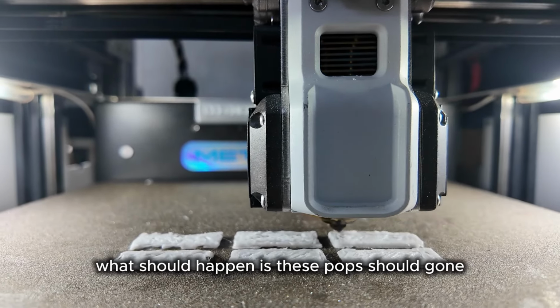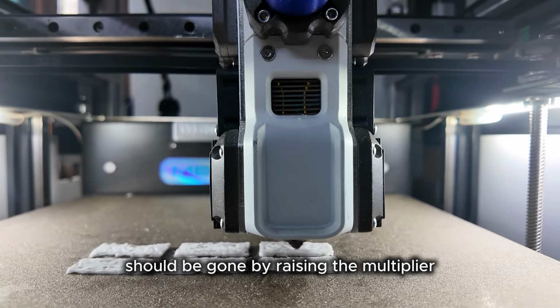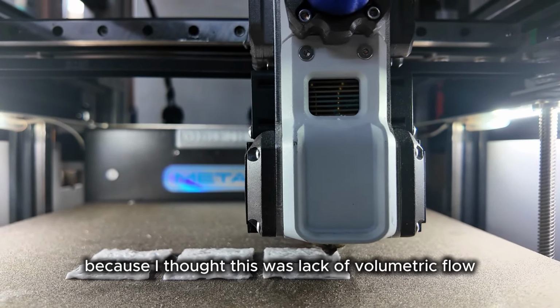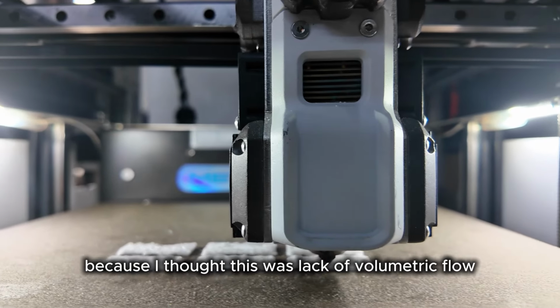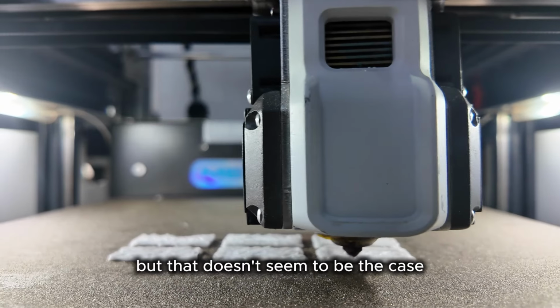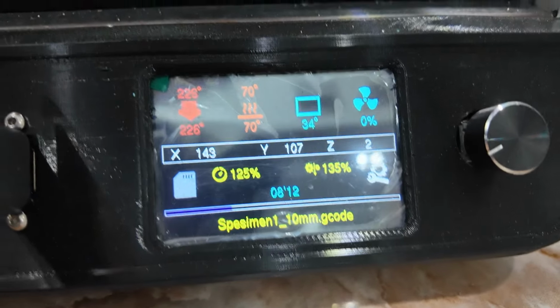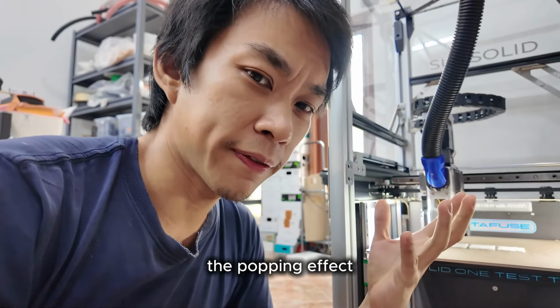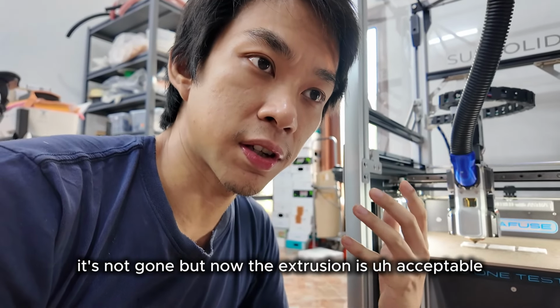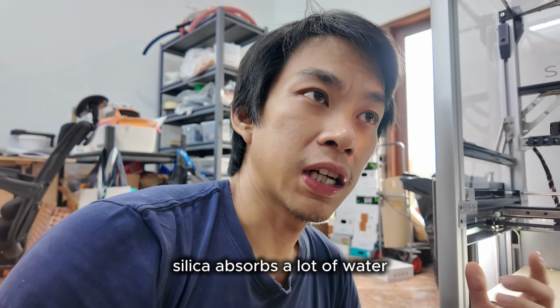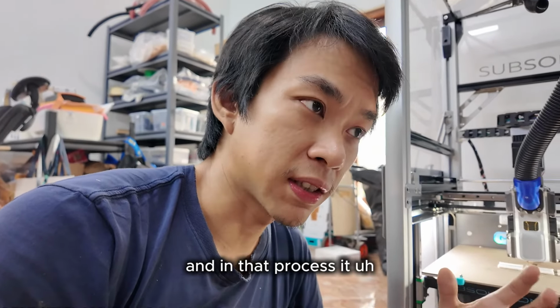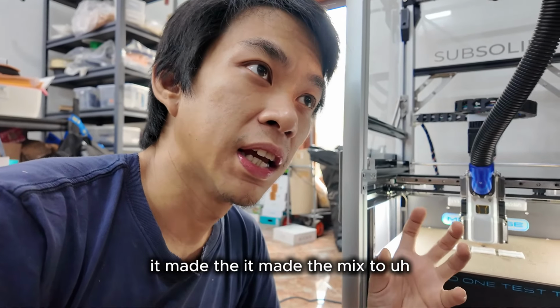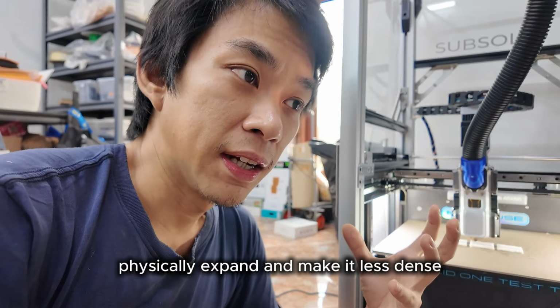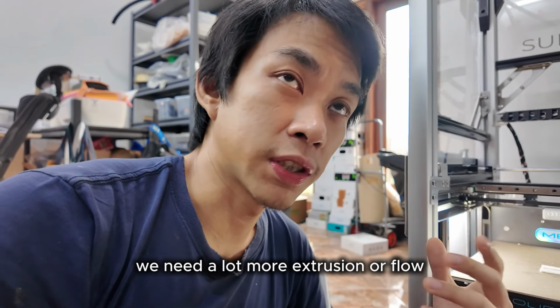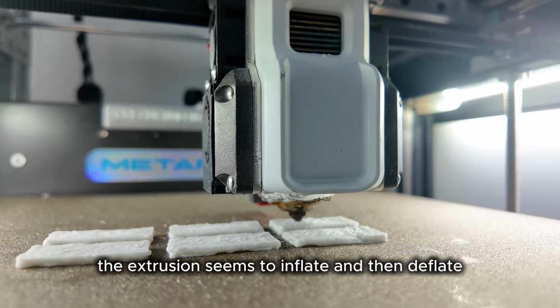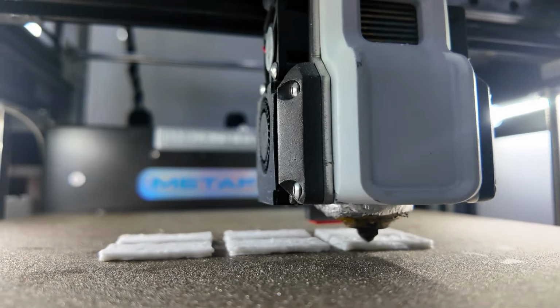What should happen is that these pops should be gone by raising the multiplier, because I thought this was a lack of volumetric flow, but that doesn't seem to be the case. Apparently raising the multiplier fixed the popping effect. It's not gone, but now the extrusion is acceptable. So I think this happens because silica absorbs a lot of water, and in that process it makes the mix physically expand and become less dense. We need a lot more extrusion or flow to compensate for that. The extrusion seems to inflate and then deflate. Look.